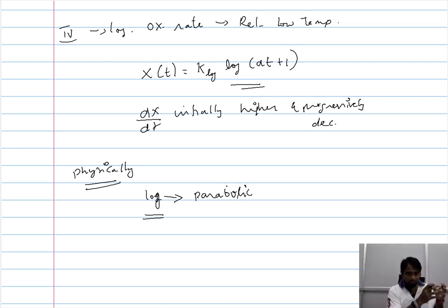So when you move away from the low temperature range, wherein the oxidation rate is dependent on time, to an average temperature in the high temperature range. Again, when we are talking about low temperature, average temperature and high temperature, all these are within the high temperature range because we are considering the high temperature range. So in the relatively low temperature range of the high temperature, you have a logarithmic oxidation rate. When you have the average temperature range within the high temperature range, then you would have a parabolic